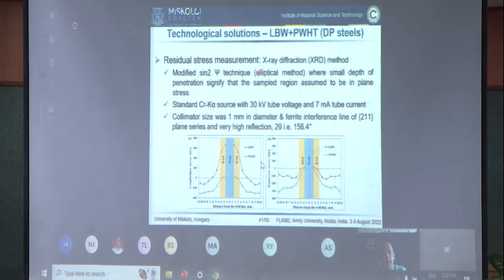Here you can see some information about the tensile test results. These joints were made as autogenous welding, so filler metal was not used. However, with filler metal, even better tensile results can be achieved. If we examine the residual stress distribution, the longitudinal stresses and the transversal stresses by X-ray diffraction, we can see that thanks to the post-weld heat treatment, the tensile residual stresses can be reduced even to the level of zero. So from tensile stresses, we can make mostly compressive stresses in the welded joints close to the surface, which can be very advantageous for fatigue loading.